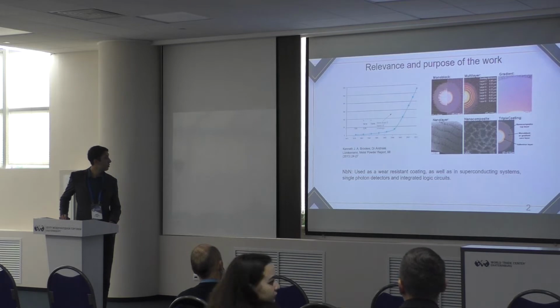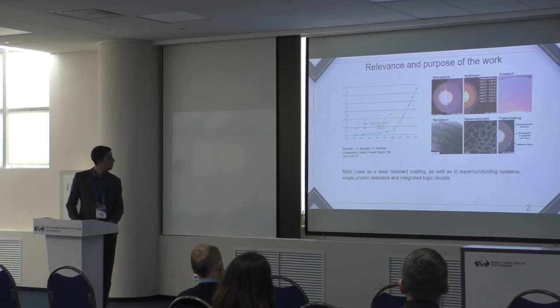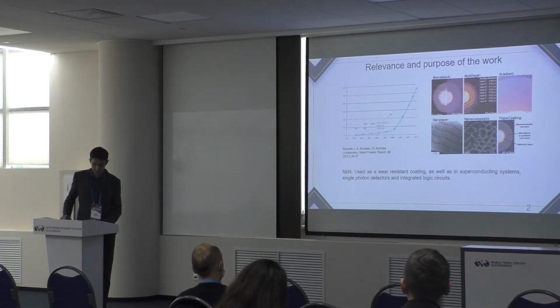surface. The thickness of such coatings can be about 5 micrometers. The architecture of multilayer coatings can be different, such as with the same elemental composition over the entire thickness of the coating. This is single layer, and multilayer with alternating layers of different elemental composition, and gradient, where the concentration of one element of the coating is changed.